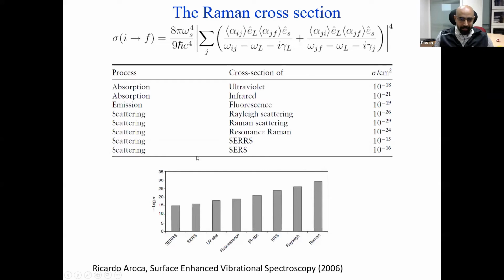So for your convenience and also for a very clear way of looking at the cross section, what is plotted in this particular graph is the negative log of cross section, which means the smaller this block, the larger is the cross section. So you can see the Raman scattering process, which scales as 10 to the minus 26 or minus 29 in certain cases where there is no resonance characteristics, is a relatively weak process, which means that the Raman cross section actually is very, very weak. Next comes the Rayleigh, then comes the resonant Raman, then the infrared and absorption process, fluorescence, and UV vis. Absorption also plays a critical role.